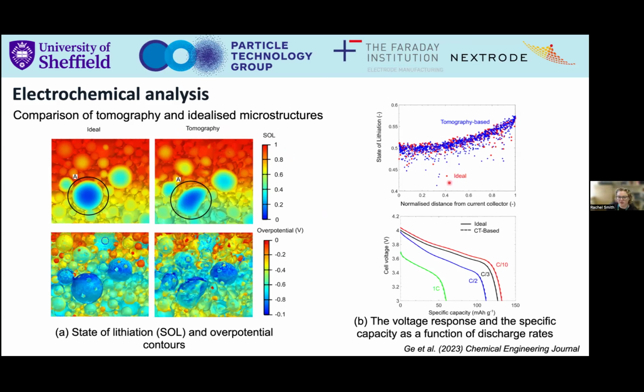And what we find here is that for our ideal case, which is the red dots, and that's talking about spheres, we get very similar mean values to what we get for the tomography based, right? So you can see the red and the blue here are in reasonable agreement. But what we found is that, yes, they're in reasonable agreement, but actually we get much more scatter with the real shape of particles than we do with the spheres, and that is to be expected. By using non-spherical particles, you effectively get hotspots of activity or inactivity, basically, because of the shape of the particle and the way the lithium travels inside the particle.